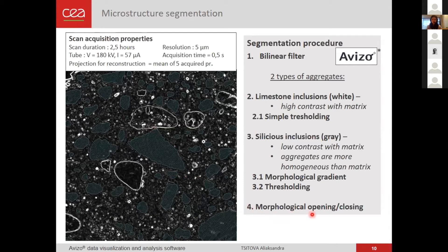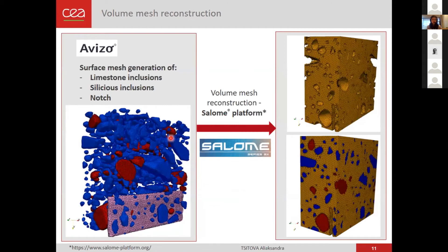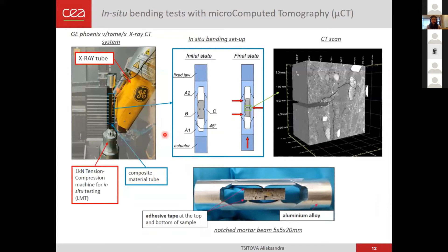We finish with morphological opening and closing operations. After segmenting the inclusions, with the same software we reconstruct surface meshes for the inclusions and the notch to represent it correctly in the final mesh. The surface meshes are then processed with tools in the free software Salome to reconstruct volume meshes. The final volume meshes are a bi-phase mesh with matrix and two types of inclusions; porosity and interfaces are not taken into account at this stage.